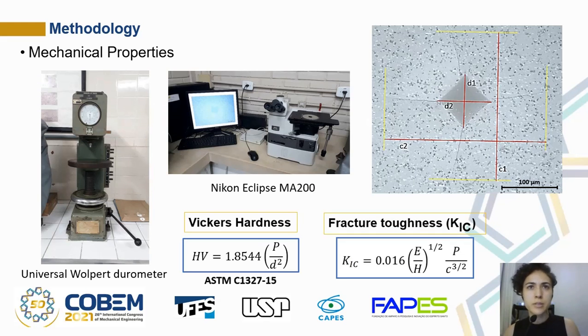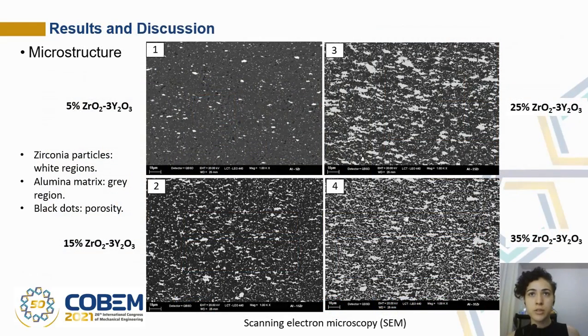Relative density was measured from this standard, which is based on Archimedes' principle. The Vickers hardness test was performed using the universal Wolpert durometer. The test was carried out following this standard, using a load of 10 kilogram force and computing values from 10 acceptable indentations. The Nikon Eclipse microscope was used to visualize and measure the indentations and the cracks generated in the samples. The calculation of fracture toughness was performed by relating the Vickers hardness, modulus of elasticity, load, and average length of the cracks.